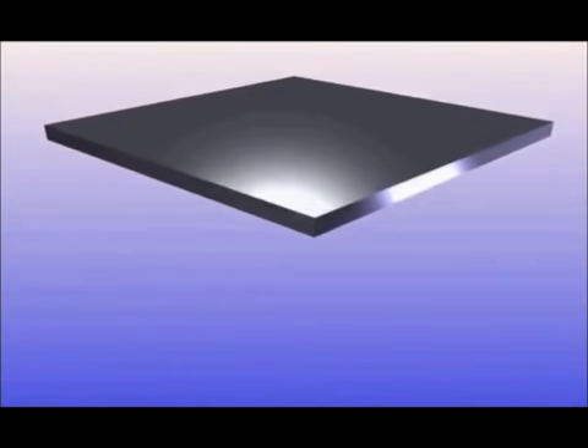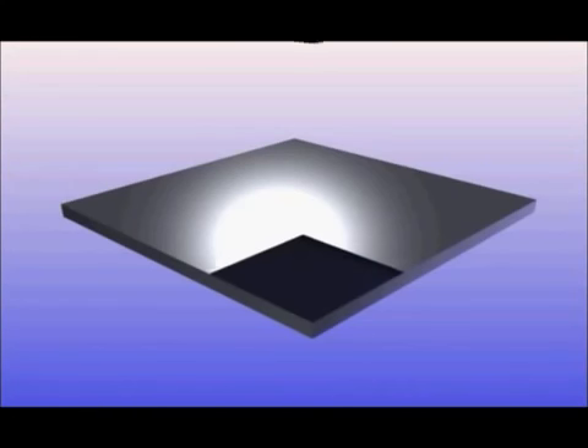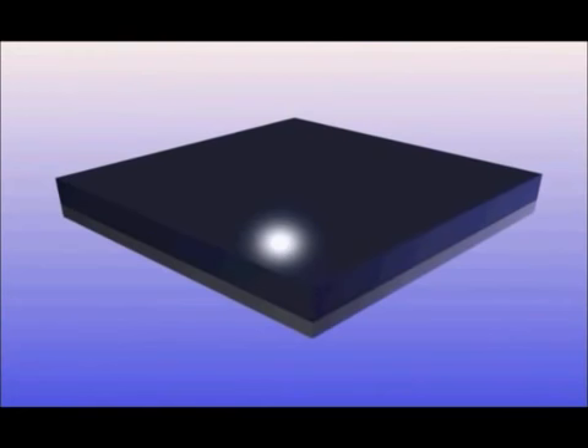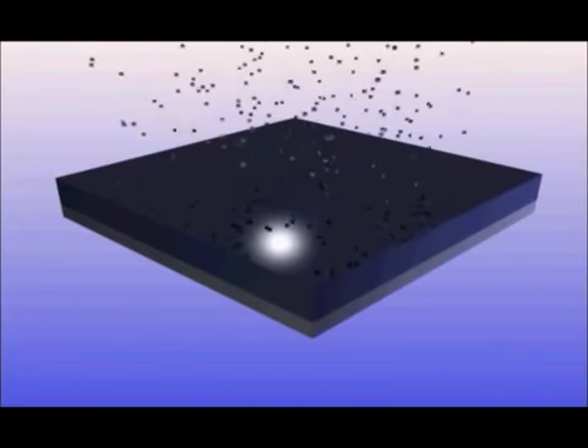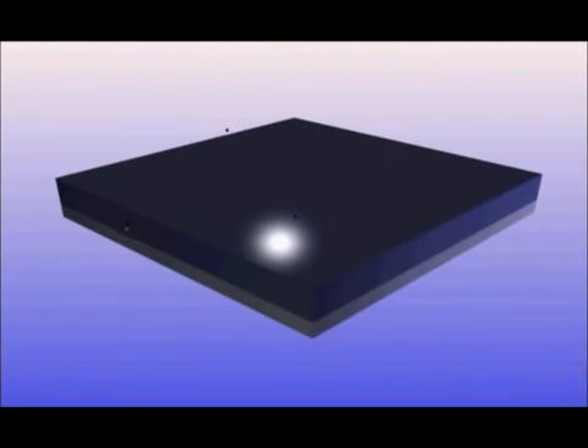Now we have all of the pieces required to construct our silicon solar cell. We start with a metallic layer, which serves as an electrical contact and as a substrate to support the rest of the cell. A thin wafer of boron-doped p-type silicon is laid down. Phosphorus is then diffused into the top surface, forming a p-n junction very near the top. With the p-n junction near the top, most of the sunlight will easily reach the junction.